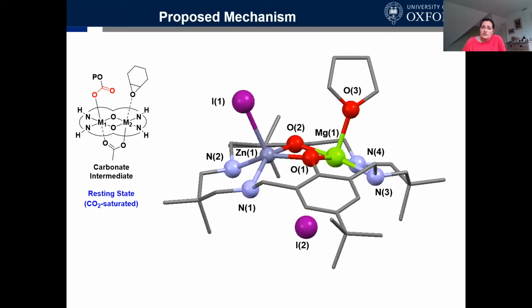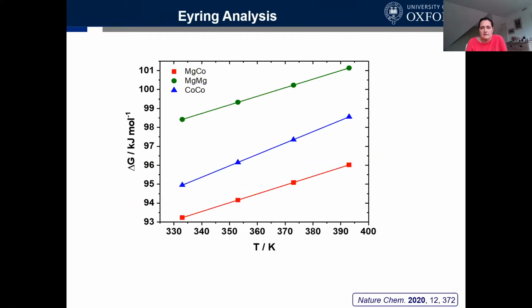Here you see an X-ray structure that confirms the idea that magnesium might be the site at which epoxide is coordinated. This X-ray structure is not of cobalt-magnesium, but of a zinc-magnesium complex. And you see that the epoxide mimic, in this case THF, is coordinated at magnesium, not at zinc. So that would perhaps be consistent with its higher oxophilicity. And that would give us the notion that it would be the other metal, zinc or cobalt, that provides the nucleophile, the carbonate, to do this attack step, the rate-limiting step.